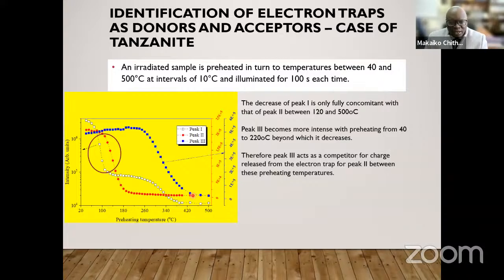So we can guess here that peak 3 acts as a competitor for charge released from the electron trap for peak 2. Because peak 1 is becoming weaker and weaker as peak 2 becomes weaker and weaker, it implies that the electron trap of peak 2 is the donor for peak 1. But these preheating temperatures should not affect the electron trap for peak 3. So peak 3 should in fact be stable. It shouldn't decrease, it shouldn't increase. But we can see that its intensity actually increases, which means that that electron trap acts as a competitor for charge released from the electron trap for peak 2.